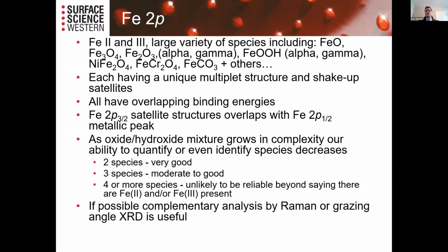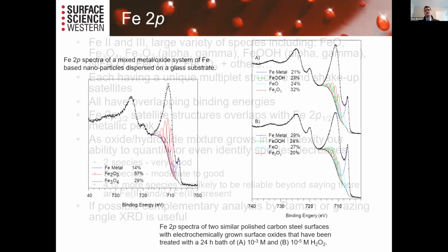They all overlap. The satellite structures from the Fe 2p 3/2 peak overlap with the Fe 2p 1/2 metallic peak. And so as your oxide hydroxide mixture grows in complexity, our ability to quantify or even identify species for iron decreases. If you have 2 species plus the metal, these work very well. For 3 species, moderate to good success, depending on the species present. And with 4 or more species, it's unlikely that you can reliably say there's anything beyond you have iron 2 and iron 3 species. So if you can get complementary analysis by, say, Raman or grazing angle XRD, that's very useful. And here are some examples of different iron species.